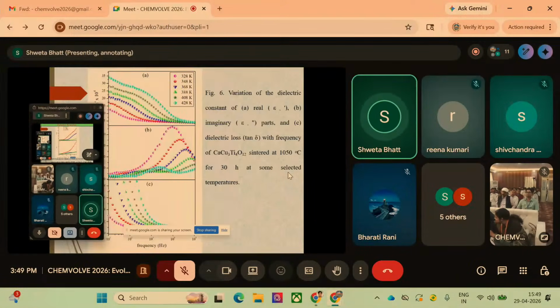So here we can say there are a large number of phenomena, Maxwell-Wagner relaxation and other phenomena. We can see that the dielectric constant varies with the temperature. But in the case of higher frequency, the dielectric constant is independent of temperature at 100 kilohertz. And we have also seen that the dielectric loss increases with the increase in temperature.